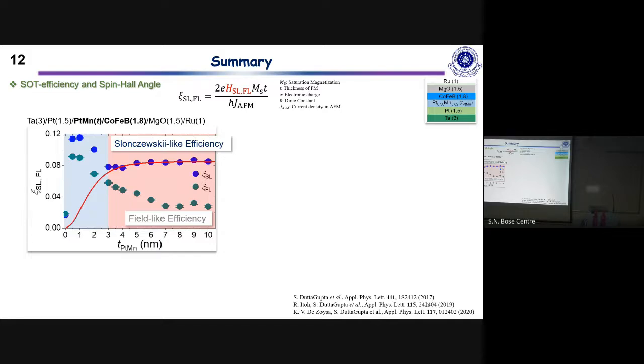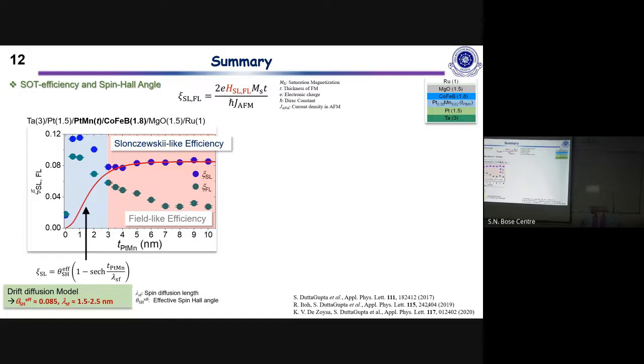And we can then fit this Slonczewski-like part, this blue data, by this equation, and we can find out the effective spin Hall angle, which is roughly 0.085, and a spin diffusion length which is around 2 nanometers. The blue data is going upwards, whereas the field-like one is going down.